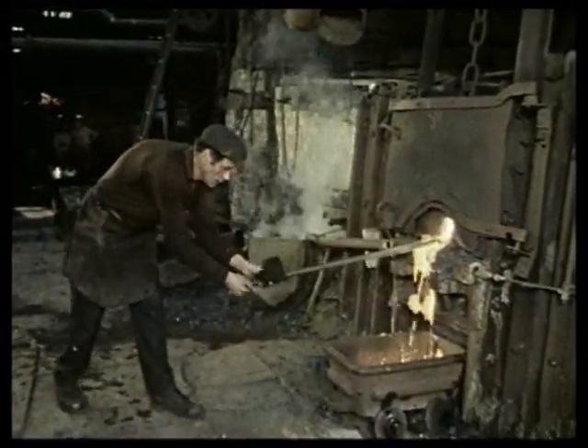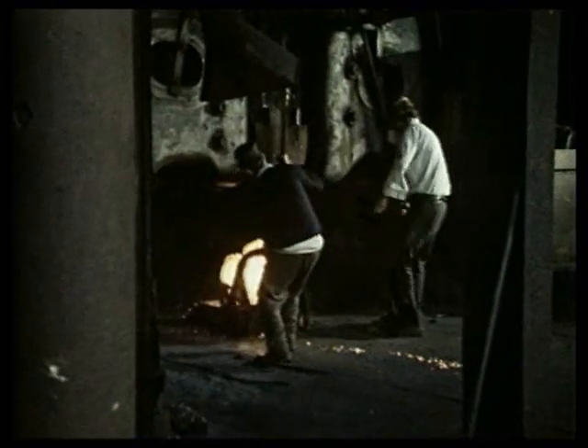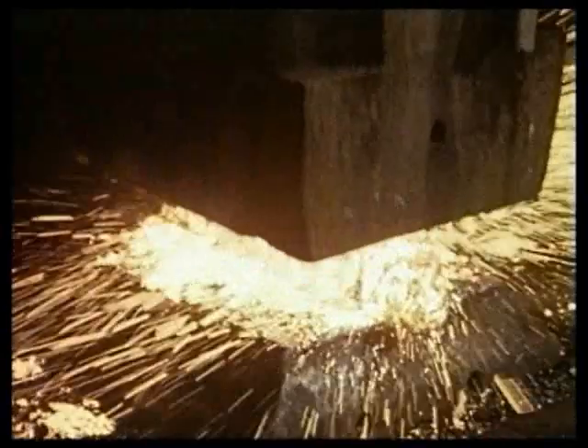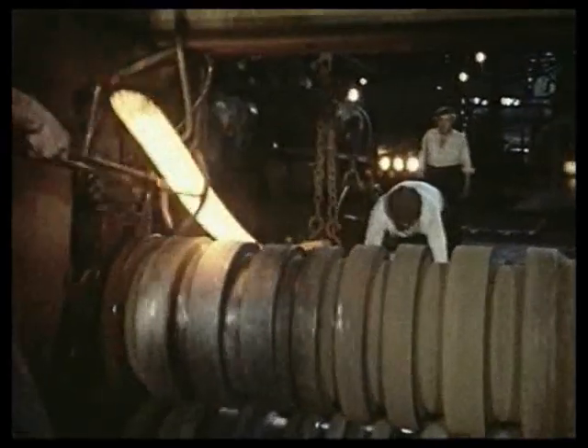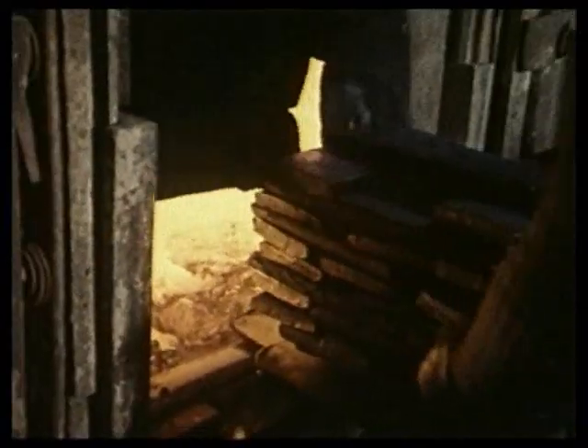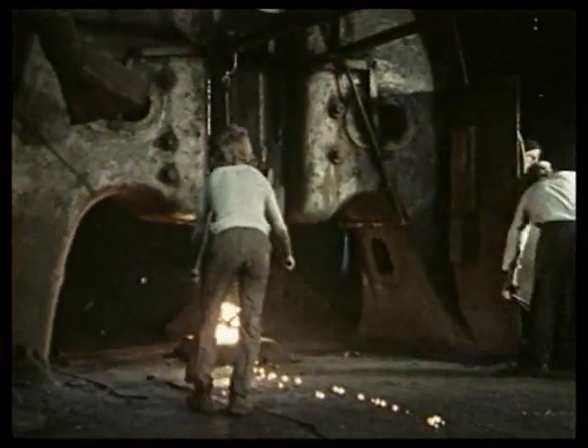It's stirred to ensure even heating, and as it becomes hotter, it's worked or puddled, then divided into 50-kilogram balls. Shingling under a large power hammer expels slag and consolidates the spongy mass into a solid billet. While still hot, this was repeatedly rolled to consolidate it further. It was then cut up, reheated and re-shingled. It was rolled again and may go through the whole process several more times, its purity and strength being improved each time it's worked or wrought.